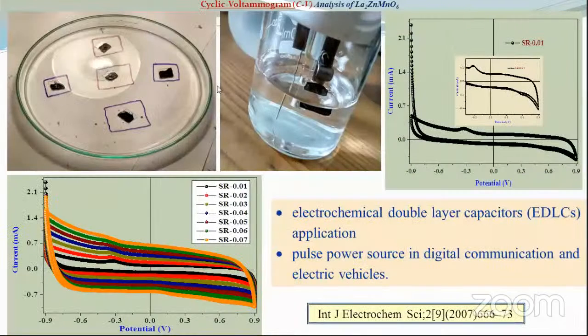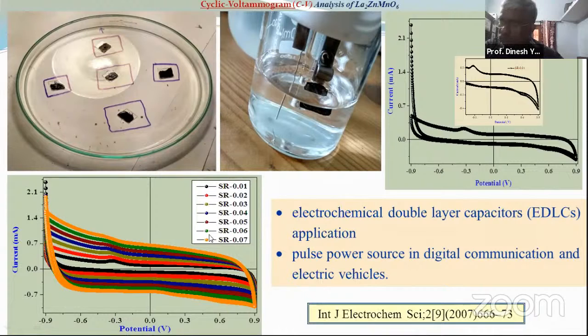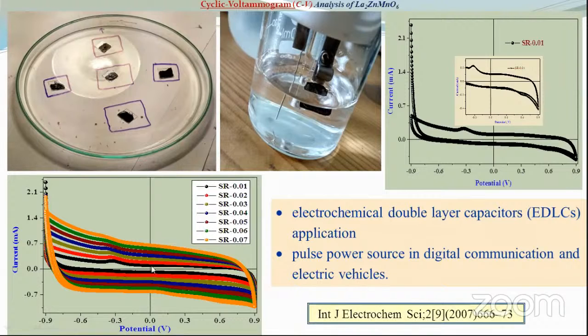And this is cyclic voltammetry. Each cycle's area increases with increasing scanning rate, which is in volt per second. This is a square type cycle, with the area increasing with the increasing scanning rate. This indicates it is useful for electrochemical double layer capacitors and pulse power sources in digital communication and electric vehicles. This shape of the loop is very much useful.